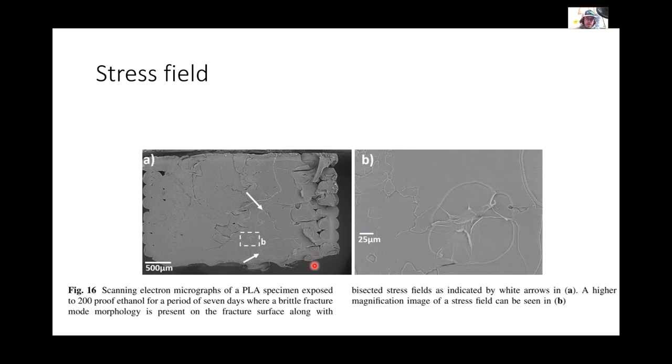What we have, and you can kind of see traces of the layer here, and it extends in. So we see the trace of the layer here, and then we see there's some defect caused by the inner layer. So it's an inner layer defect that led to the manifestation of a stress field. And again, pretty close to circular structure. And actually, we see kind of two intersecting stress fields together, both caused by inner layer defects, basically, due to the printing process.